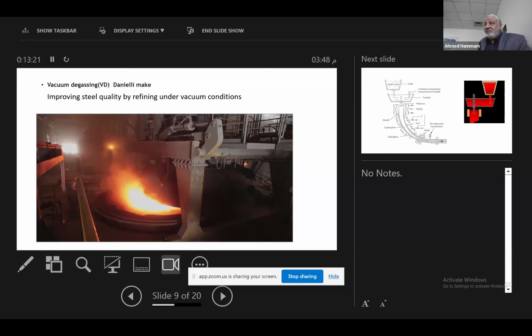And the total duration for vacuum degassing is around 30 to 31 minutes in order to reach the conditions which control the gases: hydrogen, nitrogen and oxygen also. Then we start to release the pressure again with nitrogen and purge until we reach normal atmospheric pressure.